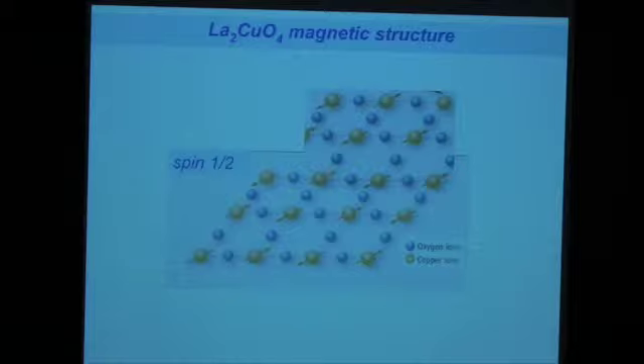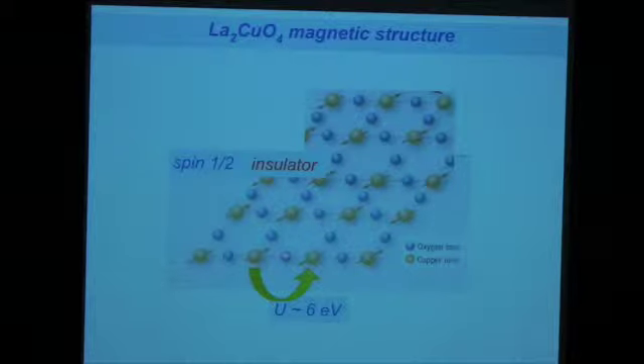So let's look at the magnetic structure of lanthanum 2 copper 04. There are spin 1/2s sitting in the plane. Here are the spins. Between the coppers there are oxygens connecting the two copper spins. It actually is an insulator, in spite of the fact that I have one electron per site, or an odd number of electrons in the unit cell, where band theory tells you that if you have an odd number of electrons in the unit cell, you should have a metal. But it's an insulator, and we know quite well why.